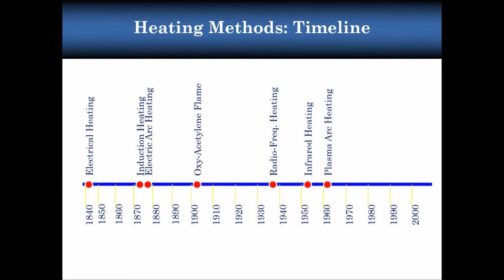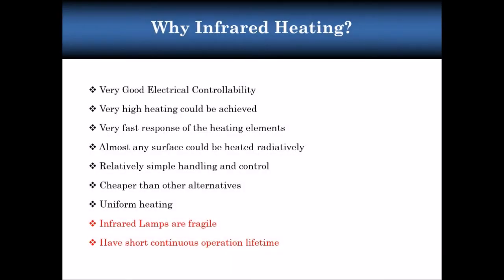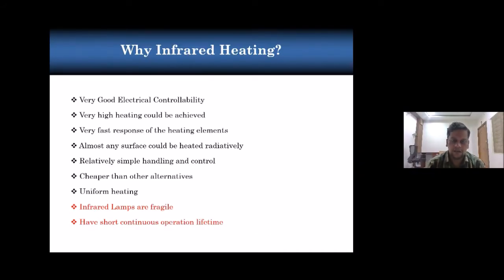Now out of these various industrial heating methods, infrared heating is used for simulating the aerodynamic heating at ground level because of its major properties, like very good electrical controllability. We can achieve any heating rate, very fast, and cooling also at a very fast rate. We can also achieve uniform heating over a very large area, not small scale. In our lab, we have tested a 1.5 meter diameter section, almost 2.5 meters in length, cylindrical sections, using infrared heaters.